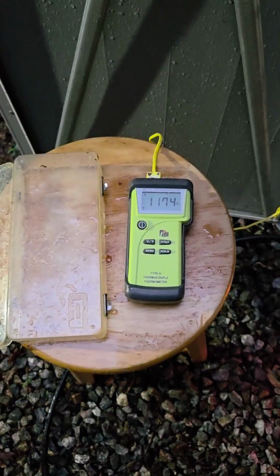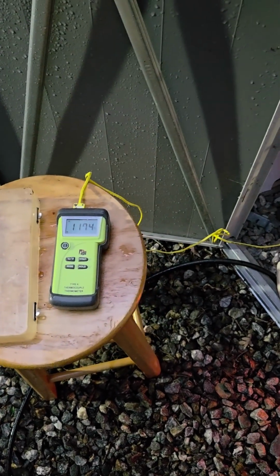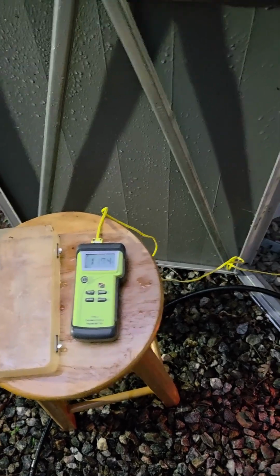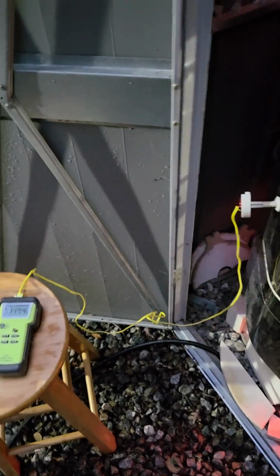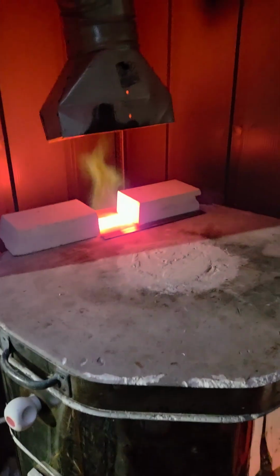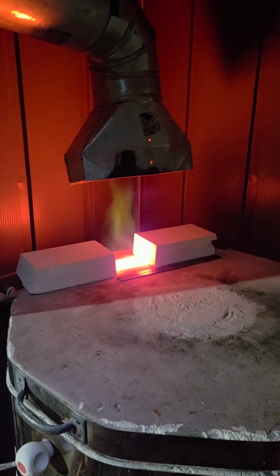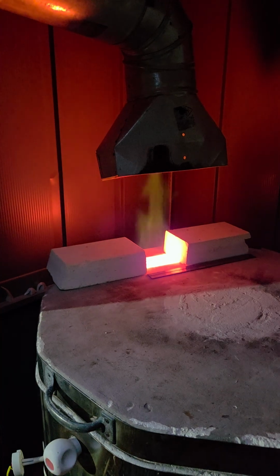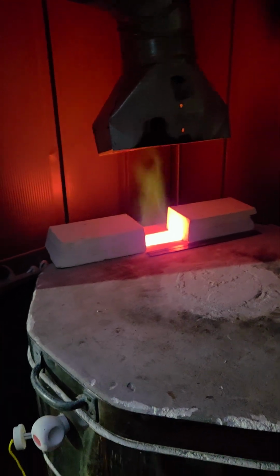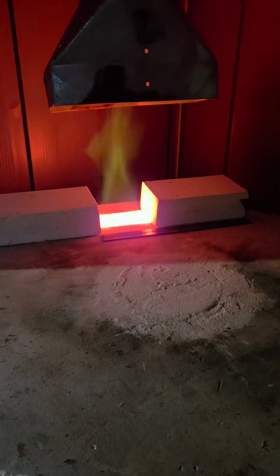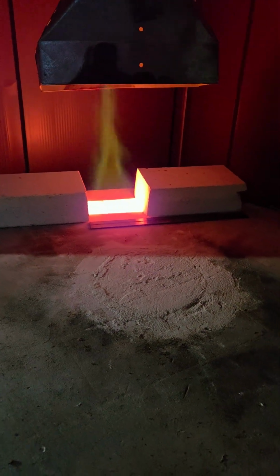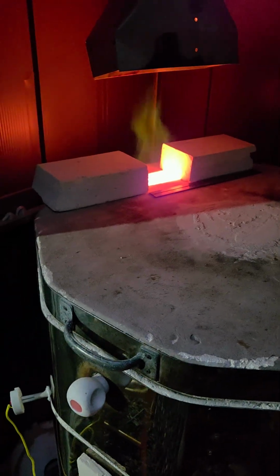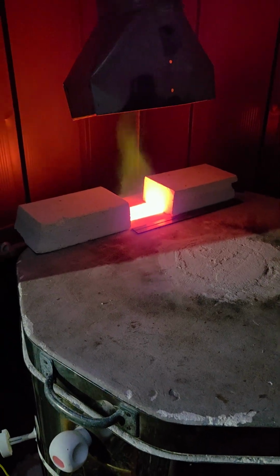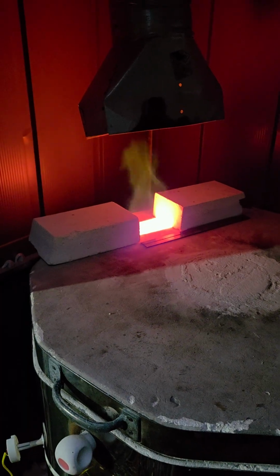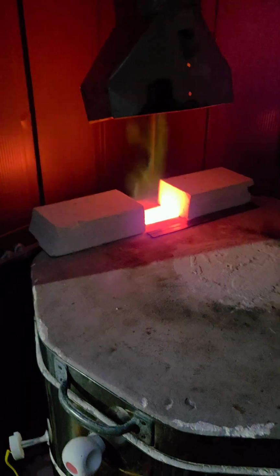It's about 8:15 and the temperature was 1174, and the climb rate had gotten down to about 74 degrees per hour. So I went ahead and opened it up about 1/4 inch, so now it's 4 1/4, keeping the pressure the same at 2.2. And once it stabilizes, I'll do another measurement and see what the climb rate is.